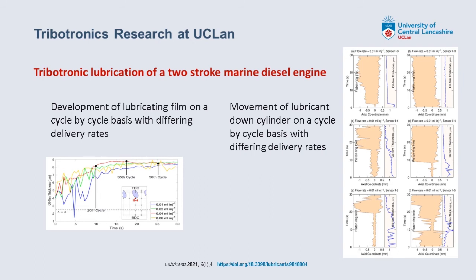These graphs represent the degree of filling of a piston ring as a function of time. And there are graphs for each of the sensors that we've put into our cylinder. So the graphs at the top represent the sensors towards the top of the cylinder where the lubricant is injected, and the graphs at the bottom represent the sensors at the bottom. The shaded part of the graph is the degree of filling between the top and the bottom of the piston ring as it goes up and down. So you can see the top two are filled fairly quickly, time starting at 0 at the bottom on the y-axis. But the lower down that the sensors are placed in the cylinder, the longer it takes the lubricant to arrive there and start to do its job.